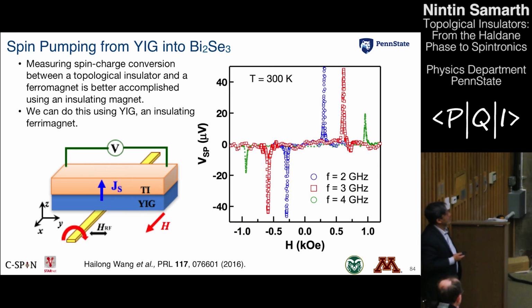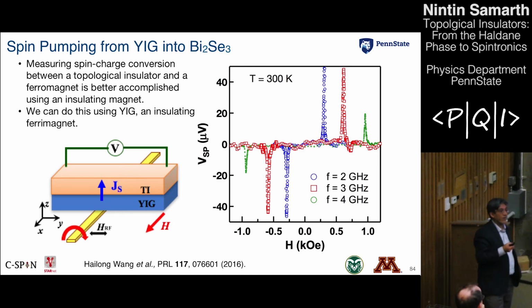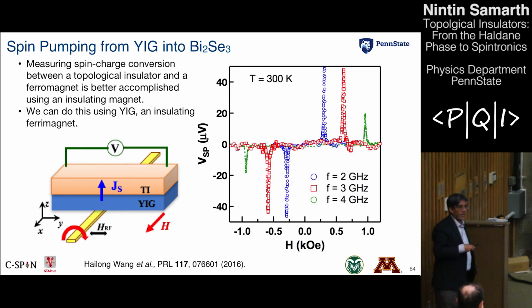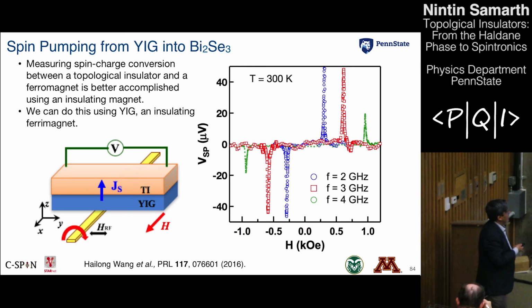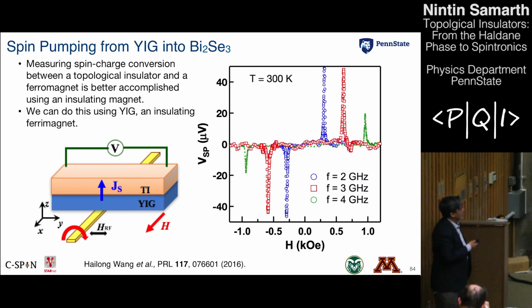But the problem, of course, is that it would be better to do this experiment by using an insulating ferromagnet rather than using a metallic ferromagnet. So this is something that my postdoc has recently done. We use a ferromagnet. It's actually a ferrimagnet, to be accurate, which is completely insulating. We then deposit this topological insulator on top, and we do a measurement that is the converse of what Dan Ralph was doing. So in this case, what we do is that we drive this ferromagnet into precession by using a magnetic field, but then we measure a voltage that's generated in the topological insulator. This is a process which is called spin pumping.